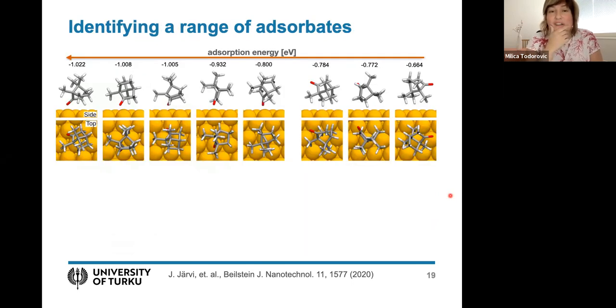And in this case, the copper 111 has six-fold surface symmetry. So the global minimum is the same in six directions. So sometimes you see the structure jump. After converging the entire six-dimensional model, we extracted all the local minima we could find, and then we relaxed all the structures. And here you can see eight unique structures that we've extracted, ranked from most strongly adsorbed on the left to weakly adsorbed on the right. And immediately we saw that there were two categories. In the five most strongly adsorbed ones, the oxygen was pointing down towards the copper surface, and in the other three structures, it was pointing up.